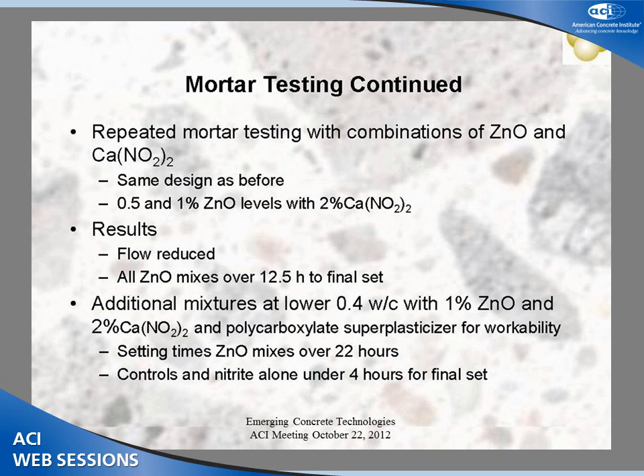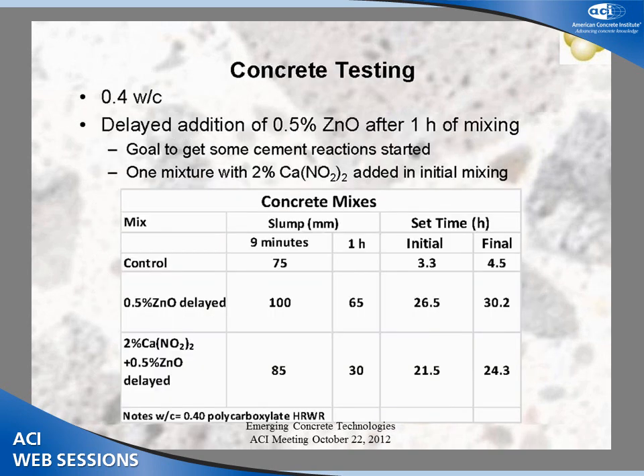So, additional mixtures were produced at a lower water to cement ratio with 1% zinc oxide and 2% calcium nitrite with a polycarboxylate superplasticizer for workability. We saw very high setting times, over 22 hours, compared to the control and the calcium nitrite mixtures that had set times under 4 hours, time to final set.